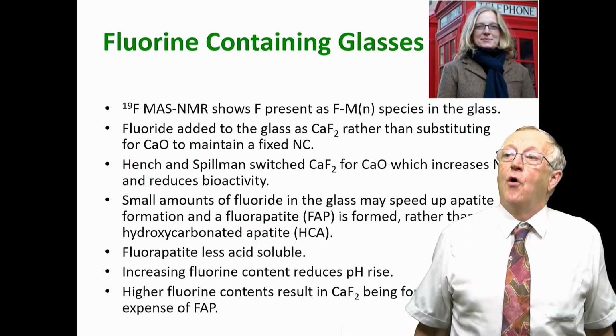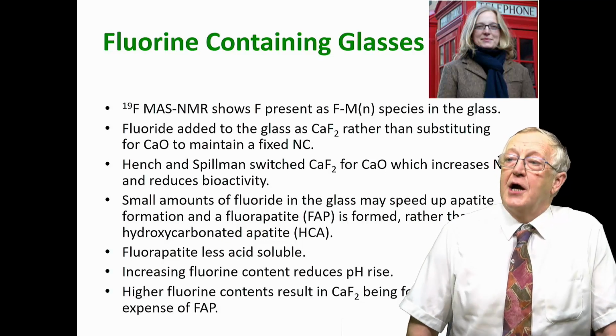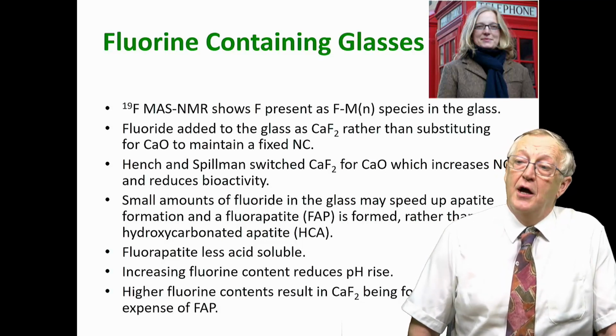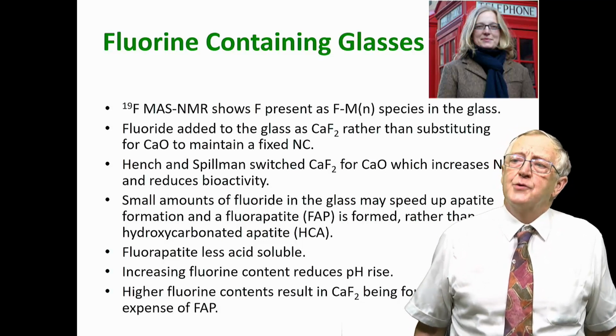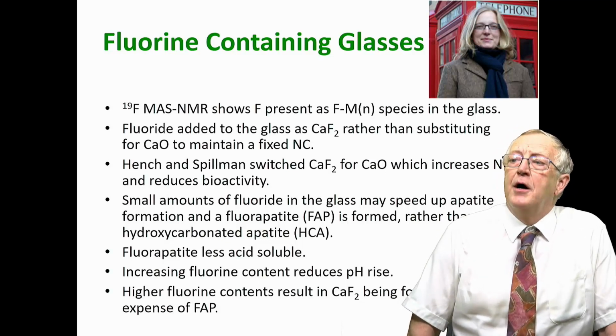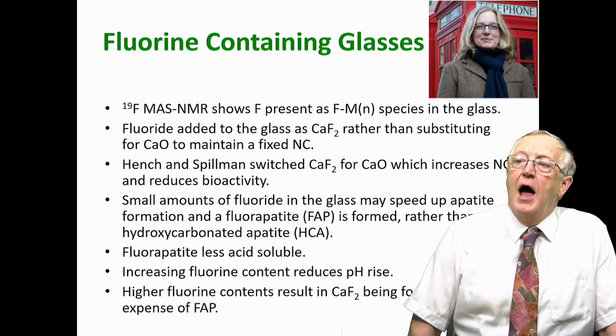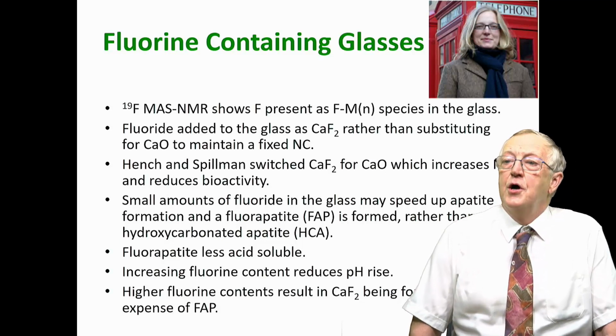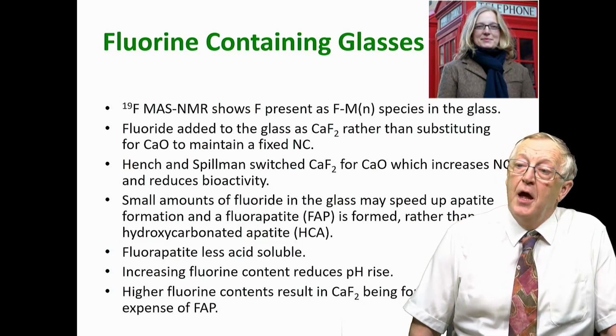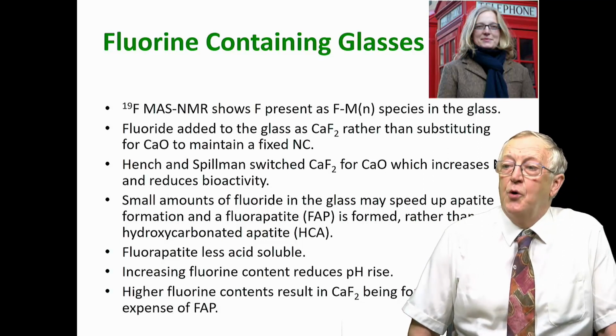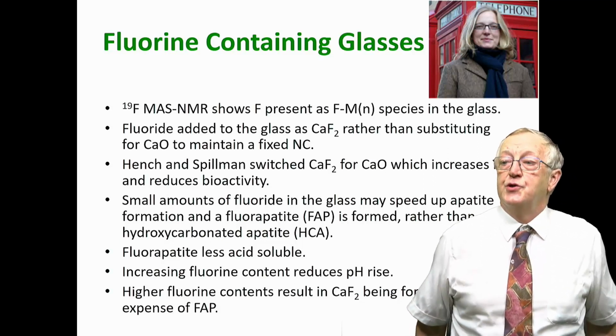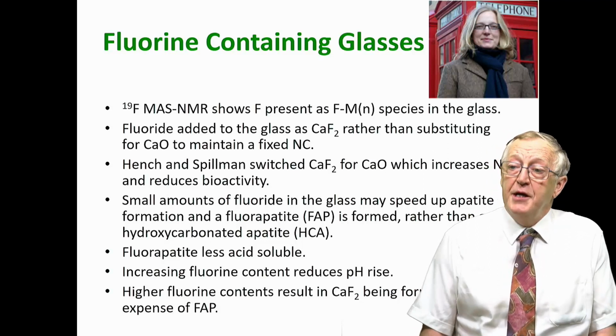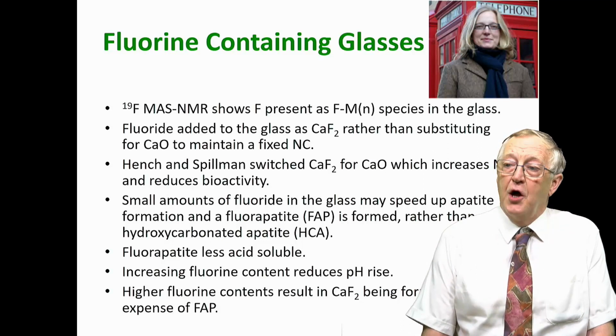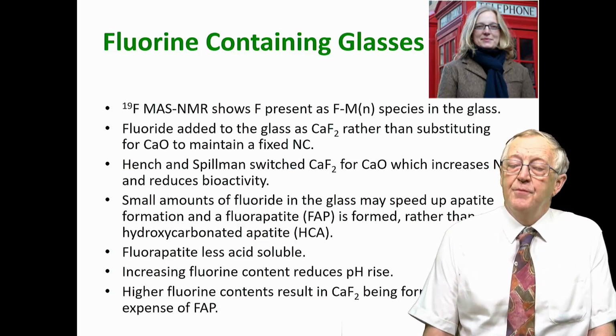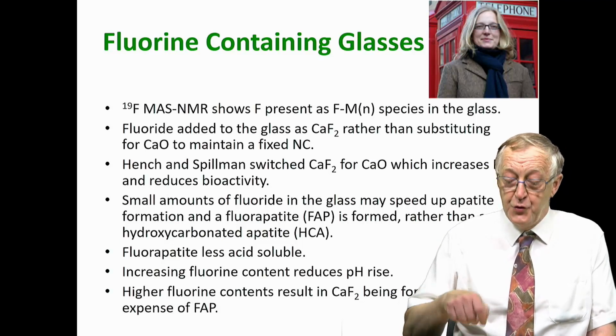And this contrasts, as I said before, with Spilman and Hench, who swapped calcium fluoride for calcium oxide, which reduced the bioactivity. Small amounts of fluoride in the glass speed up the apatite formation, with fluorapatite being formed rather than hydroxycarbonated apatite. And fluorapatite is much less acid soluble, and increasing the fluorine content also reduces the pH rise slightly. You have to be careful, because if you add too much fluorine to the glass, what you form is calcium fluoride, or fluorite, rather than fluorapatite, the fluoride analogue of the mineral.